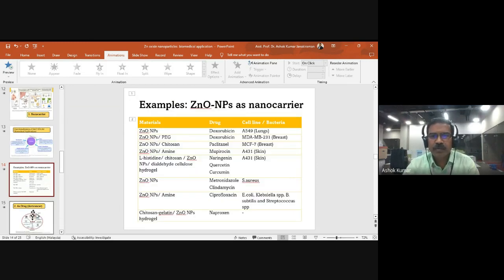Some examples of zinc oxide nanoparticles have already been published in reputed journals. Zinc oxide nanoparticles with doxorubicin were checked against lung cancer cells to ensure the activity. So it already has activity, that means it kills the cancer cell line. They have already proven it in vitro. Likewise, we have zinc oxide nanoparticles with polyethylene glycol, with chitosan, and with amine. Then we have chitosan zinc oxide nanoparticle, dialdehyde cellulose hydrogels. This may be for a topical application.